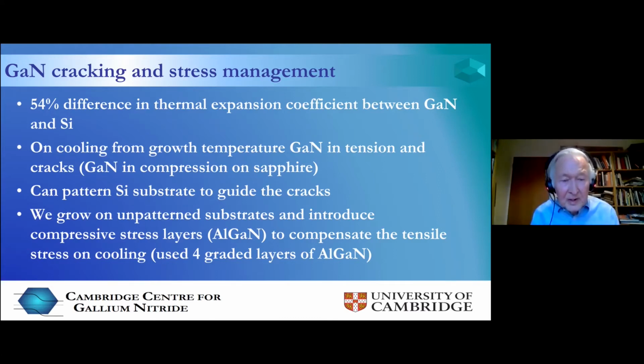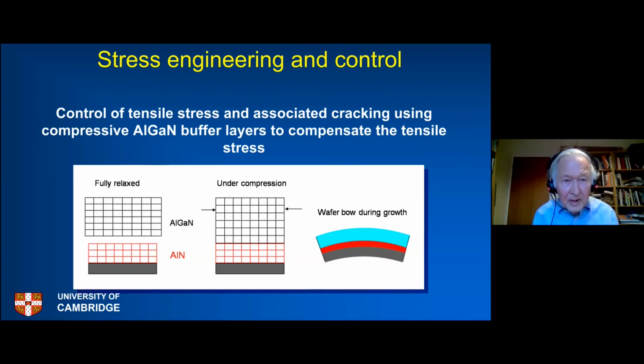So on the left-hand side of this diagram, the gray portion at the bottom is a silicon wafer. Then we grow aluminium nitride on top of that. And then we deliberately grow aluminium gallium nitride on top of that. And the unit cell, that's the atom spacing in aluminium gallium nitride, is greater than in aluminium nitride. And so when you grow aluminium gallium nitride epitaxially on the aluminium nitride underneath, the aluminium nitride acts as a template, and so the aluminium gallium nitride is under compression, and you deliberately introduce the compression layers, which counters the tensile stress when you cool down, which would happen otherwise, and so you don't get the cracking.